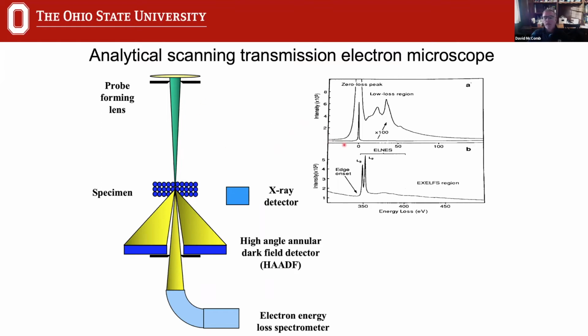And of course, what we actually see in our spectrum is the largest peak is going to be what we call our zero loss peak or our elastic peak, because this is a thin specimen, and typically these are high energy electrons, and therefore the most likely thing to happen is absolutely nothing. And so the fast electrons pass through the specimen, they don't lose any energy, and we get a peak in our spectrum at zero energy loss.